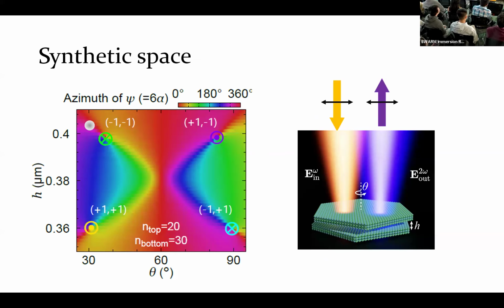And we can use them as a so-called synthetic space. So if you just imagine these two knobs as two coordinates in a kind of virtual space, we can actually see that these virtual spaces have some pretty cool properties. This color map shows you the polarization of the light that is generated as a function of these two variables, H and theta, for two layers of HBN. So we continuously tune both the interlayer spacing and the twist angle, right? And each spot shows you the polarization. And there are these peculiar singularities in them. Actually, there are 4 of them in this space.